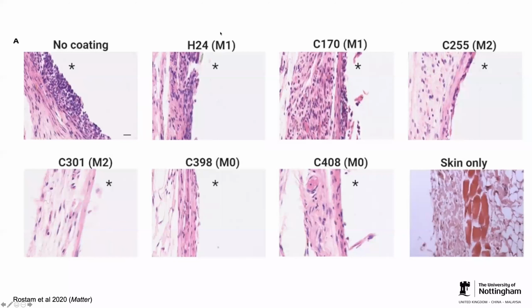For example, for the 2 M1 polymers that are pro-inflammatory, you can see that the level of cell infiltration is pretty much similar to what we have for uncoated. And for the 2 polymers that are M2 polymers, the 255 and 301, you can see that there are far fewer cells that have infiltrated the immediate vicinity of the implanted catheter. And then the 2 polymers that represent naive macrophages. So these are polymers that don't influence macrophage polarization status. They're highly attractive for these cells, but they don't influence the phenotypes. Basically, they maintain a neutral phenotype, a naive phenotype.